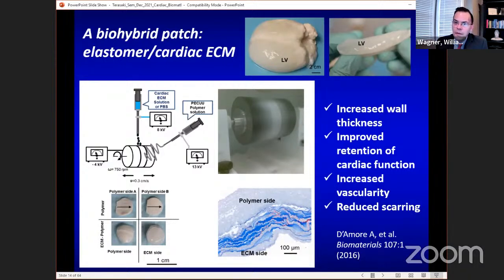And if you know Murphy's Law, if you have an open face peanut butter and jelly and it drops, it lands jelly side down 100% of the time, right? That's the law. So what we wanted to do is that same thing with the jelly side down onto the heart. So we wanted ECM side rich down onto the heart, because that would allow those factors preferentially to diffuse and transport towards the heart and encourage cells to grow up from the heart. So that's what we did. I'm not going to show the data, but basically compared to a control without the ECM, reduce scarring, increase vascularity, improve cardiac function, all these things.